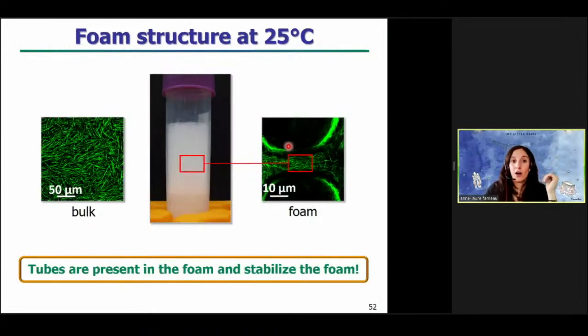Then to understand how the foam is stabilized, we just stain a tube solution with a fluorescent probe, as you can see here in bulk, with confocal microscopy. We produce again a foam by hand shaking from this stained tube solution. We took a few bubbles of the foam, and we observe again by confocal microscopy the presence of tubes inside the foam liquid channel in very high quantity. So tubes are present at the interface surrounding the bubbles and in very high quantity in the liquid phase. So it's really the presence of these tubes that stabilizes the foam and leads to this ultra-stable character of the foam.